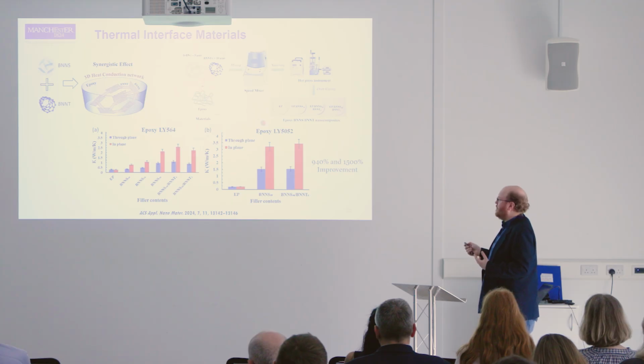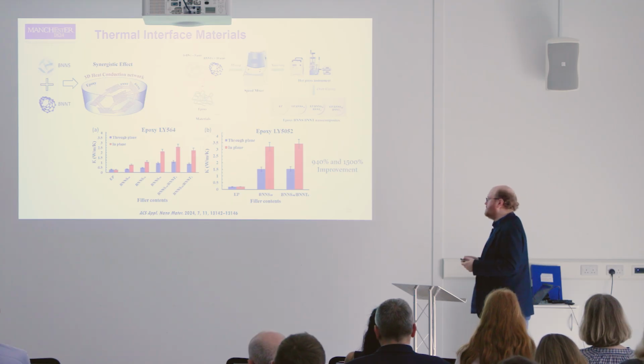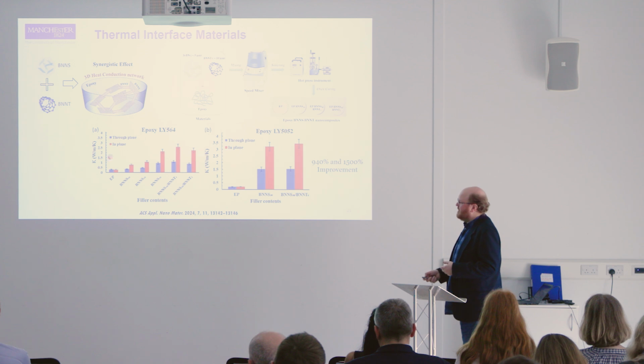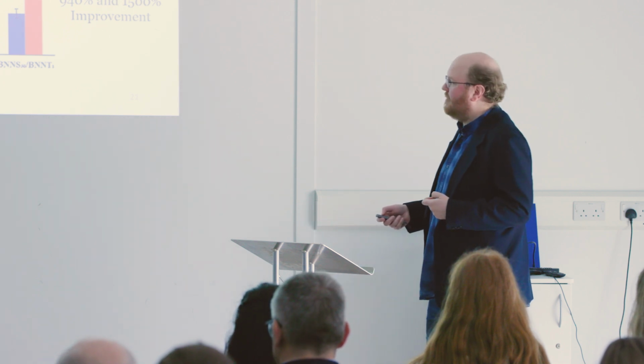So this work was looking at them in epoxies as a thermal interface material, and we can see this is the thermal conductivity of the neat epoxy, and as we add more nanosheets, or when we have a composite of nanosheets and nanotubes together, we see a difference of the in-plane and through-plane thermal conductivity as well, whether we're going this direction or that direction.